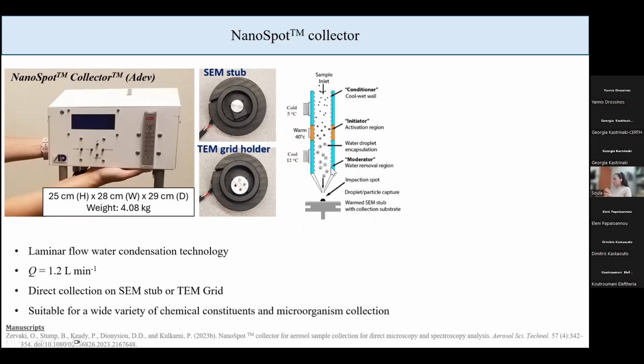The mixed stream subsequently flows through another cold stage, where the growth of the droplets is enhanced before it gets concentrated into a small beam through a converging nozzle, and it gently impacts on the warm surface of an SEM stub or a TEM grid holder. This way we can collect the sample directly on a surface that is required specifically for these analytical procedures without having to deal with handling of the sample, transferring, and having losses through these processes.